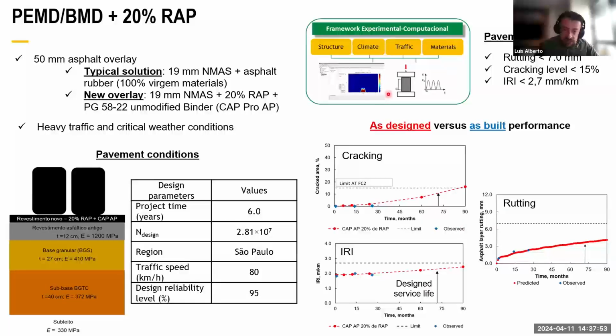So we applied the material in the field. The material has been there about 2.5 years, and the blue points are the observed ones. So these are very nice results, because regarding IRI, we are in the model, and the fatigue cracking too. In the last field inspection, we could see some small cracks starting to appear. So it makes sense, because our model is saying that it's time for the cracks to appear. And for rutting, which was the big concern of the people from the agency, we did this prediction, and the blue points are following our prediction. So very nice results here, and the material is there.